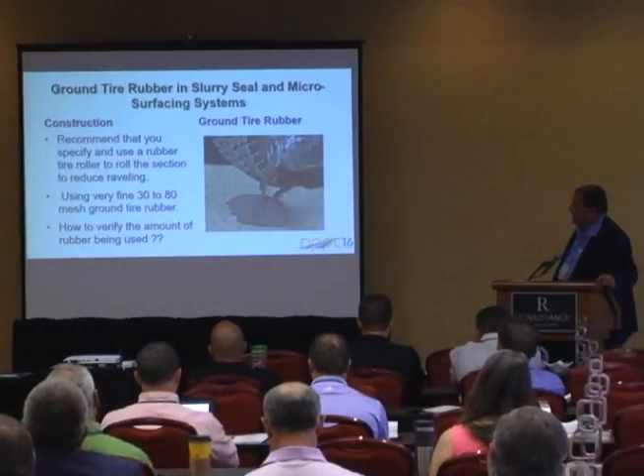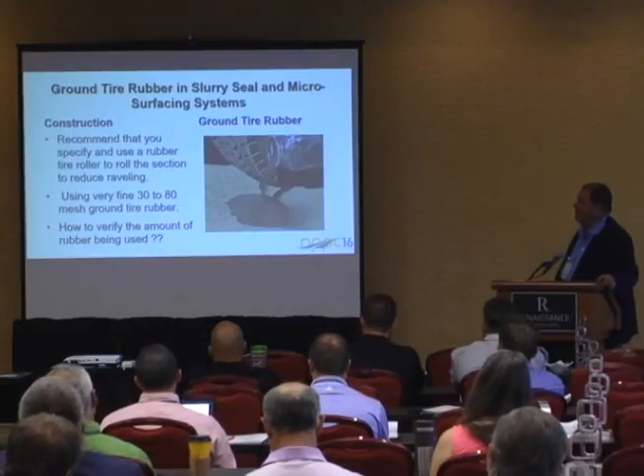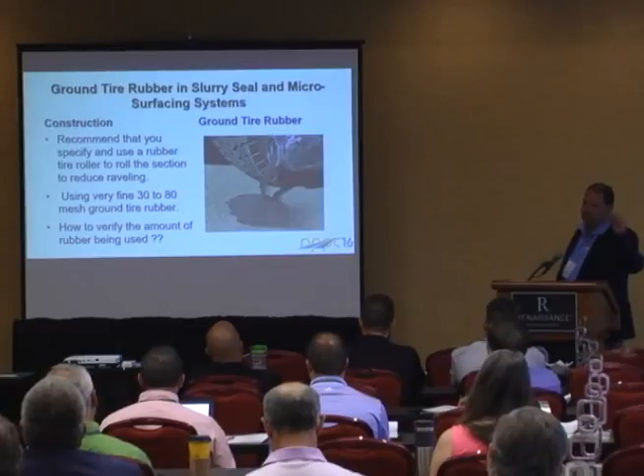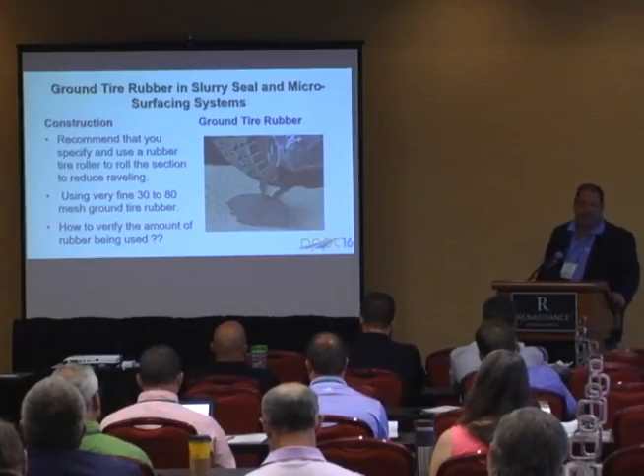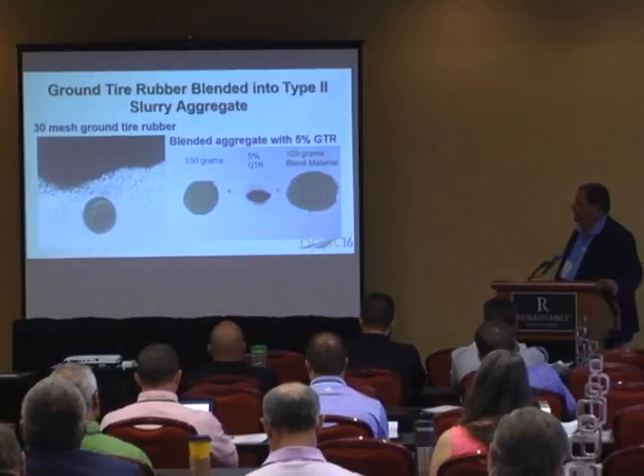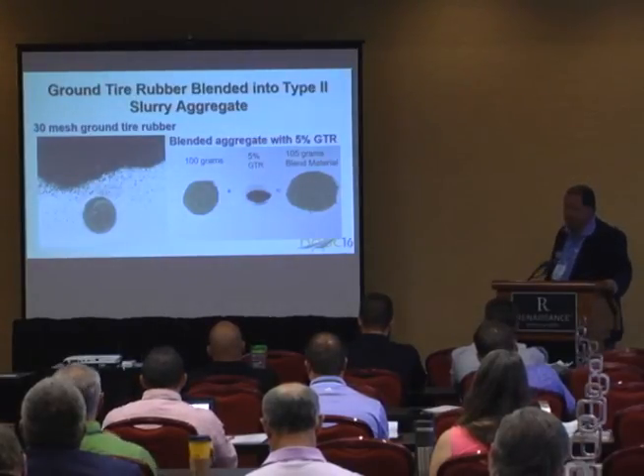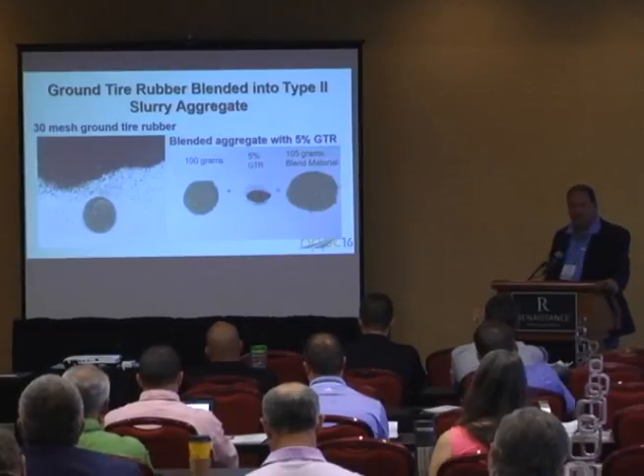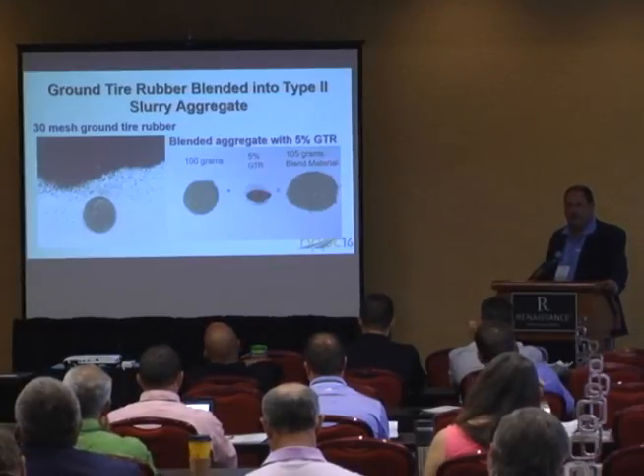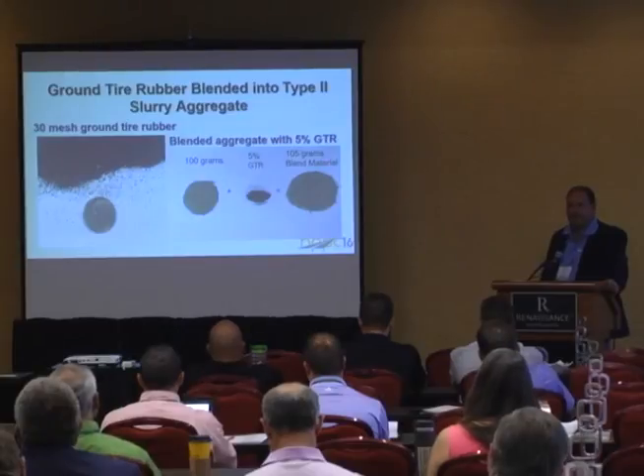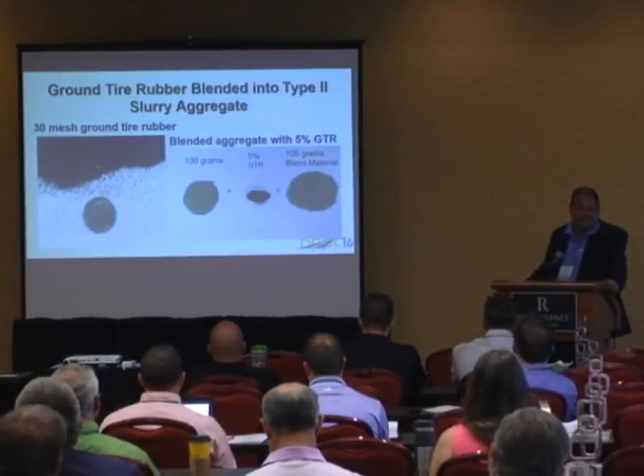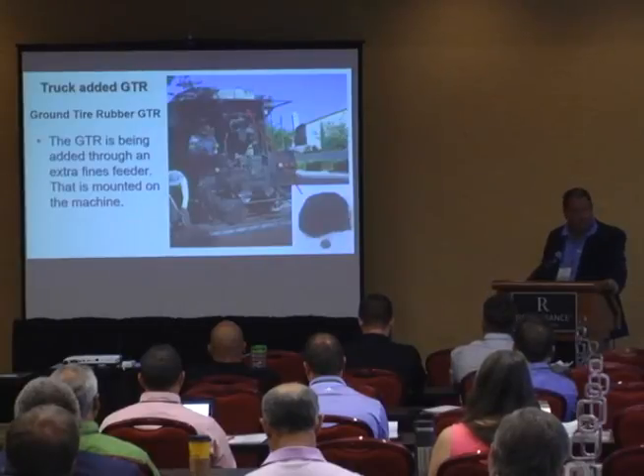There we go, making those tires. You want to use a very fine mesh, 30 to 80 mesh ground tire. We don't want to use anything larger because of the rebound effect. We want to really just use it as a mineral filler or a filler in the aggregate gradation. Here's an example of blending with the aggregates. You have 100 grams of rock, you add 5% by weight, and you blend the 2. There you go. I guess the only visible difference is one looks a little darker maybe on the right, but not noticeably.